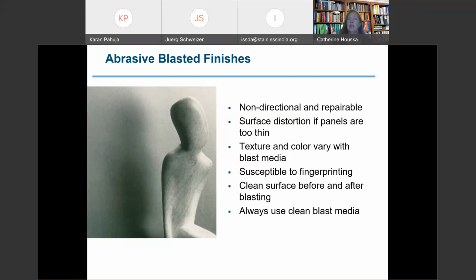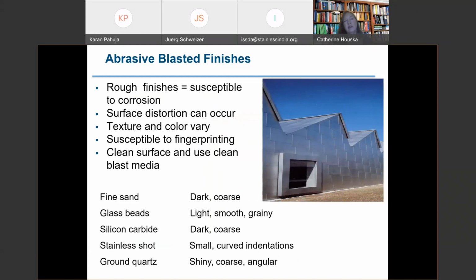It will show fingerprinting, and anything like markers or paint, anything that might get on an abrasive blasted surface can be difficult to remove, especially if it's a very aggressive abrasive blasting pattern. So there are different media that are used. The rougher the surface, the more susceptible it is to corrosion. Fine sand and silicon carbide, which tend to produce a darker, coarser finish, also tend to have the most problems with corrosion. Glass beads or stainless steel shot have a surface that is more smoothly rolling under magnification, so those are less susceptible to corrosion, but it's still a rougher finish. So you have to consider what's appropriate.